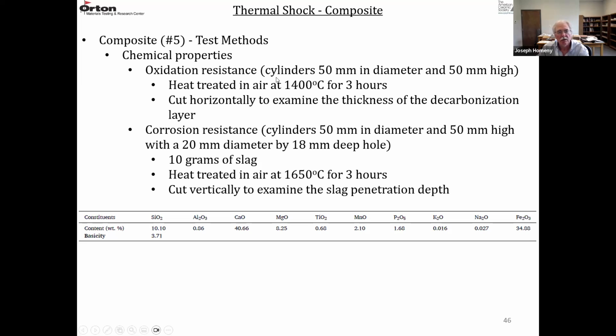They heat treated these cylinders in air for 3 hours at 1400 degrees C. And then they cross-sectioned the cylinders in the horizontal direction and measured the decarbonization zone, the thickness of that layer. There are other ways to measure oxidation resistance, like thermogravimetric analysis, where you get a quantitative number. And the corrosion resistance is also qualitative.